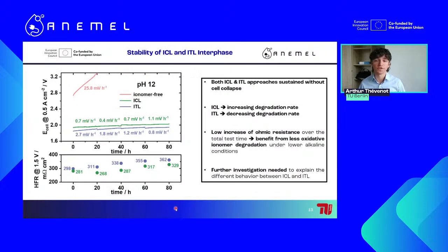After having this performance test, we wanted to have a stability test of the ICL and the ITL interface architectures, to first see if it would be collapsing just as with the ionomer-free version, or whether we would see different behaviors. And thankfully, it did not collapse, so we were quite happy about this. The behavior is also quite interesting, because for the ICL, over the 80-hour test, we see only a very slight increase in degradation rates, while for the ITL, we see a slight decrease of the degradation rate over the 80-hour test.